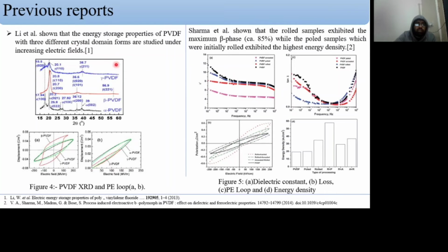Li et al. show the comparison of polarization of beta phase, alpha phase and gamma phase. Here we can see beta phase has a very good polarization or ferroelectric loop compared to alpha and gamma, but gamma also has a better ferroelectric loop compared to alpha.